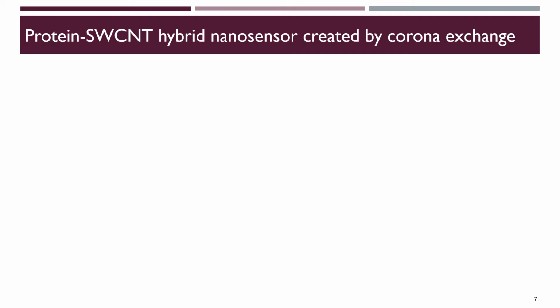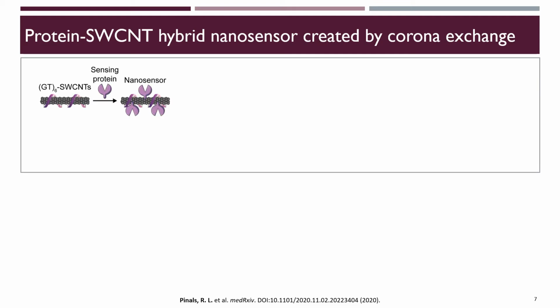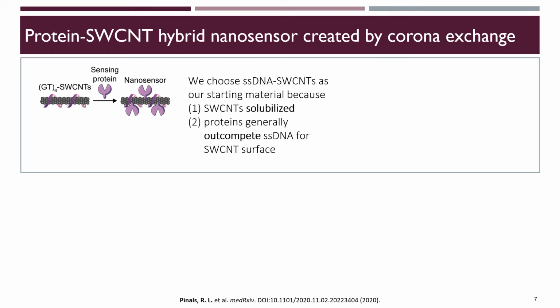To construct this CoV2 nanosensor, I employ a passive immobilization strategy, beginning with DNA-solubilized carbon nanotubes. Carbon nanotubes by themselves are extremely hydrophobic and not water-soluble. Therefore, we must employ probe tip sonication with amphiphilic polymers, such as DNA, to suspend these carbon nanotubes in aqueous solution. I chose to then implement this passive corona exchange from DNA to proteins rather than directly sonicating with the proteins in order to maximally retain the protein secondary structure. Further, my prior work has indicated that proteins generally outcompete DNA for the carbon nanotube surface, and we hypothesized that this membrane protein would display innate affinity for the graphitic carbon nanotube surface.